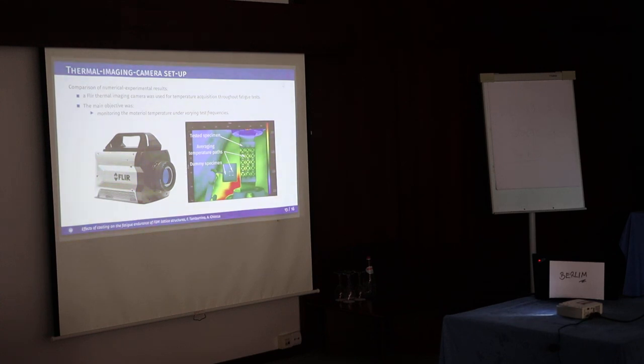Yeah, not too high. I've never wanted to be too high. Be careful, but maybe have good calculations. Maybe the structure of the lattice in that case, you have enough air flow. For this reason we started testing at different frequencies to see the temperature behavior and to understand it. We all know there is heat generation inside polymers and there can be thermal runaway, and then the polymer is completely gone. But it didn't happen. We had tests lasting for two days sometimes at 3 Hertz to reach long cycles. At 20 Hertz, sometimes we had a specimen lasting one day to reach some medium cycles. We never had really thermal runaway. The temperature was always like probably one degree more than room temperature, so we never really reached really high temperature.